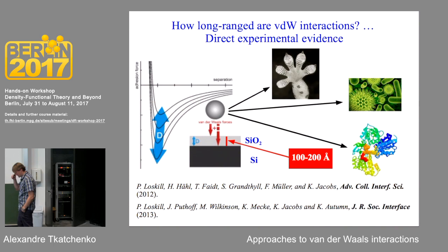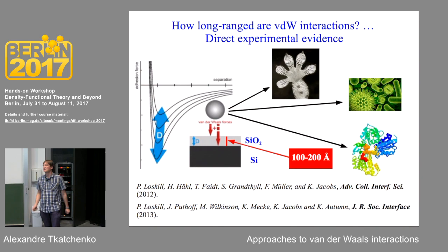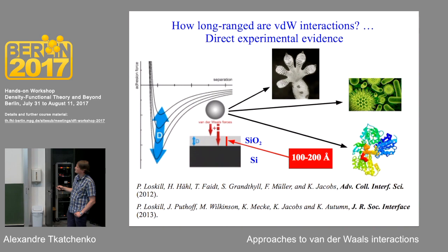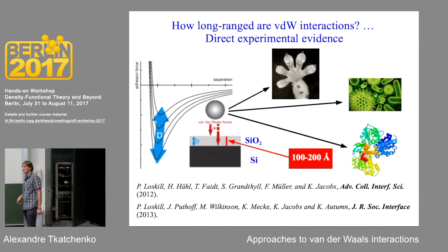This is not exclusively theoretical: experiments by the group of Karin Jacobs in Saarbrücken measured how van der Waals force scales with thin film size of silicon dioxide grown on a silicon surface. They observed that force saturation only occurs when the thin film thickness exceeds 100-200 Å — a 10-20 nanometer range — consistent with our calculations. Experiment thus agrees with theory that van der Waals interactions are very long range, far beyond a pairwise sum of C6 coefficients.